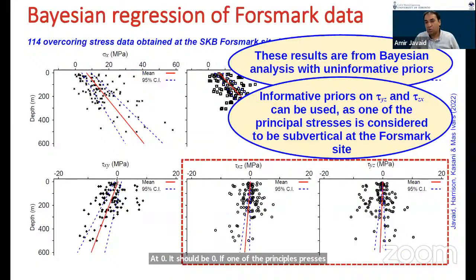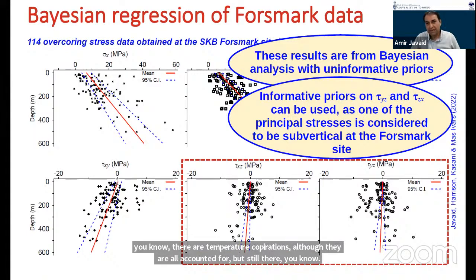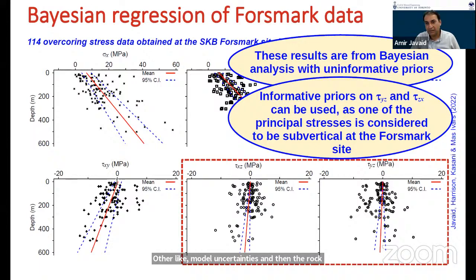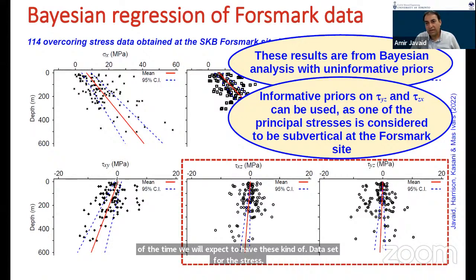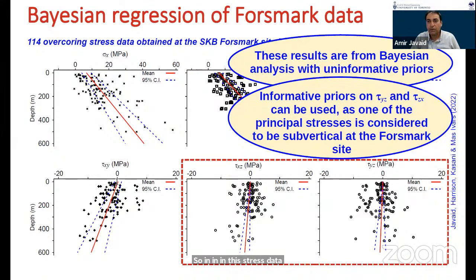But what we're getting from this noisy data, and noise in data is due to many factors. There are temperature considerations, although they're all accounted for, but still there are model uncertainties, and then the rock mass variability, and all these factors contribute to this huge variability. Stress data is rarely a neat data set or less variable. Most of the time, we would expect to have this kind of data set for stress. So the variability is huge, but I think it's reasonable to believe that the mean is somewhere at zero.